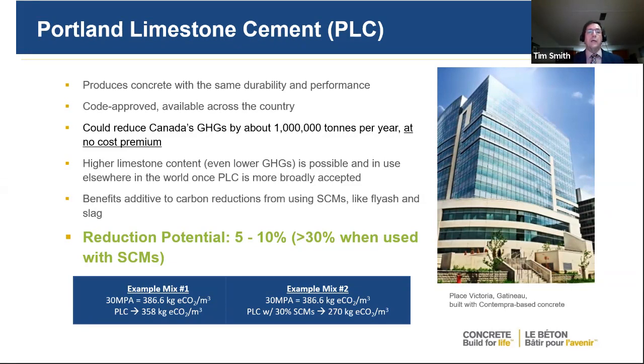There are higher limestone amounts available, as they use in Europe. But right now we're just using the up to 15% that's been approved in the CSA standards. Benefits also can be increased by utilizing supplementary cementing materials. So if you use the Portland limestone cement and then use up to 30% supplementary cementing materials, you can see that in the example I said, a 30 MPa concrete would have 386 kgs per cubic meter of attached CO2. But if you use the Portland limestone cement with 30% SCMs, you're down to 270. So that's a tremendous reduction available if you start to utilize the Portland limestone cement with the supplementary cementing materials.